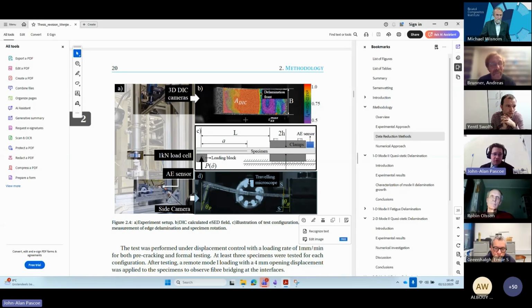We also had some multi-directional specimens, and then of course you see a much stronger twisting of your crack front. But that indicates some sort of asymmetry, I would say, in the layup or in the test setup or something.